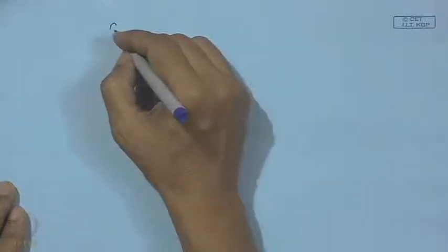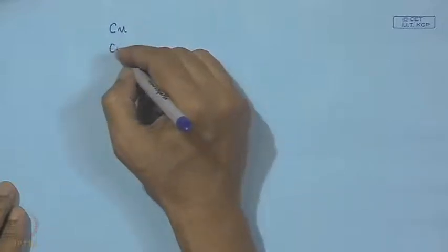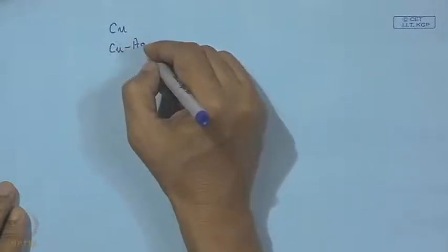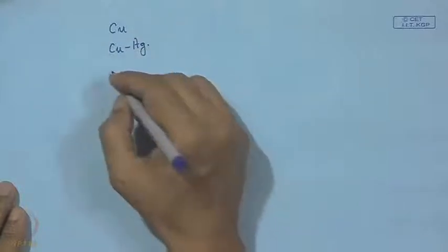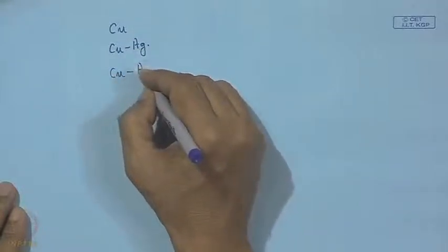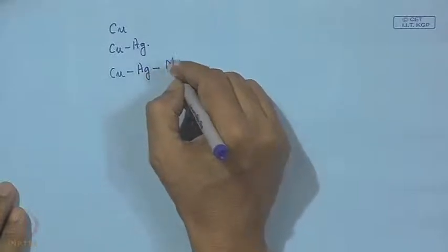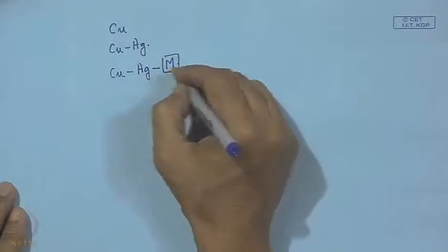It can be an inert atmosphere flushed with argon, reducing means enriched with hydrogen, or it can be high vacuum. Under that environment, this is supposed to have spontaneous spreading. But here comes the question, whether we use a pure metal or a binary alloy or even a ternary alloy, that means silver, copper and M. Now, what is the role of this M?